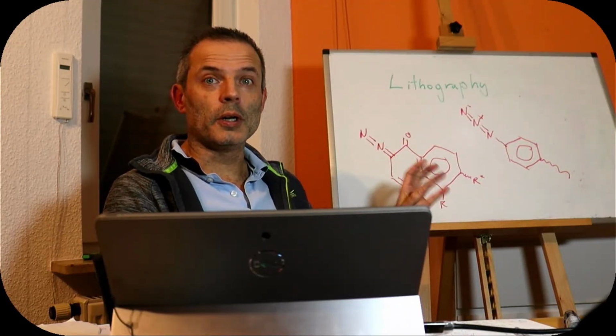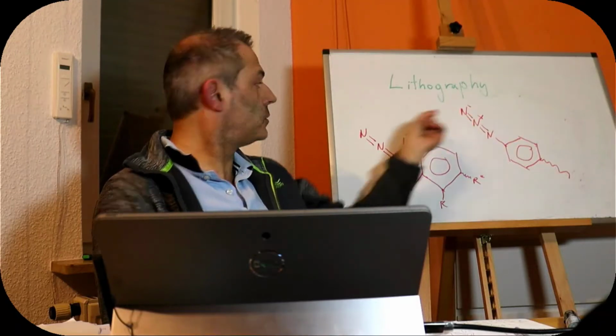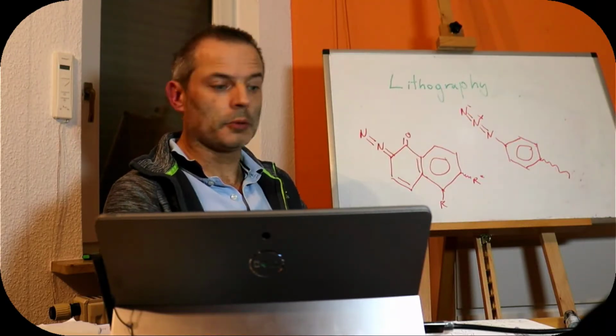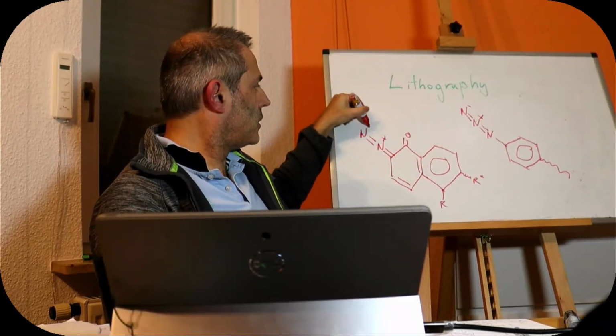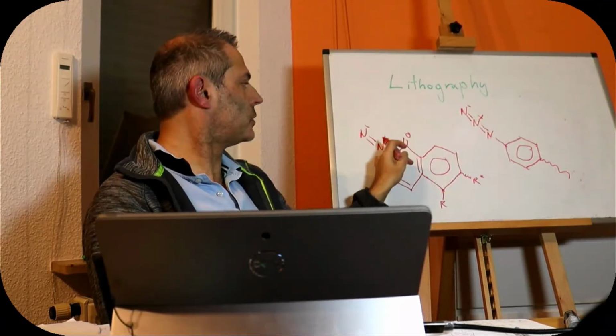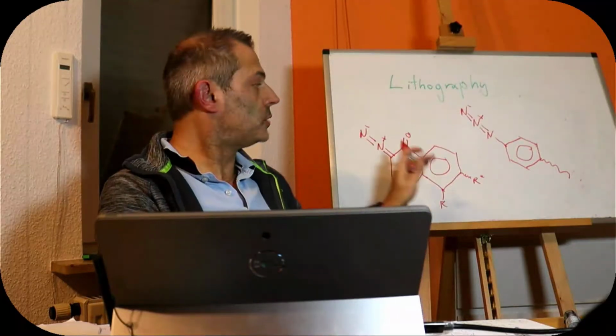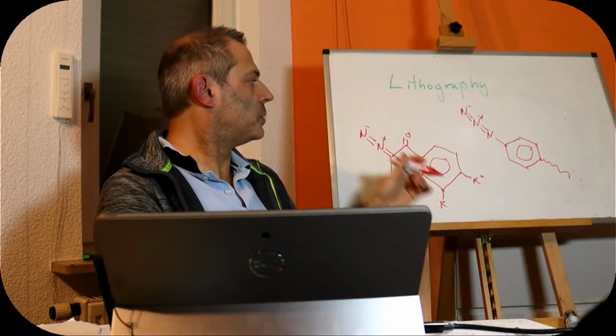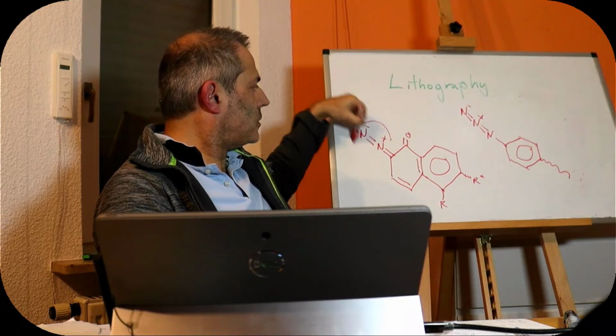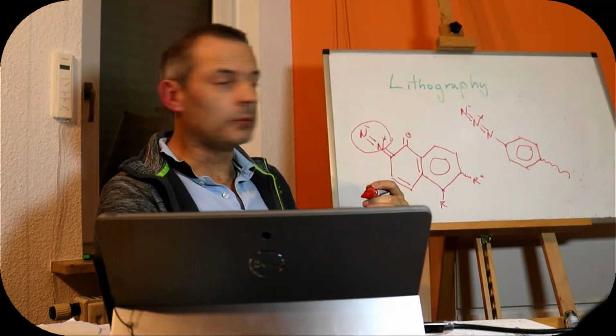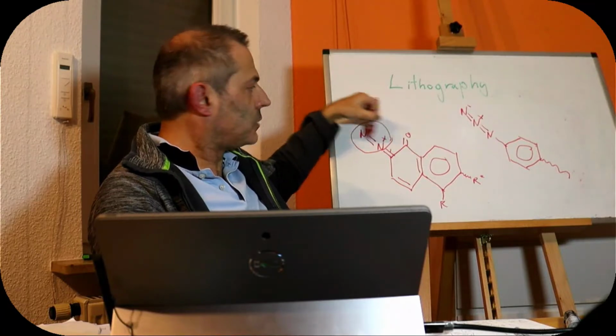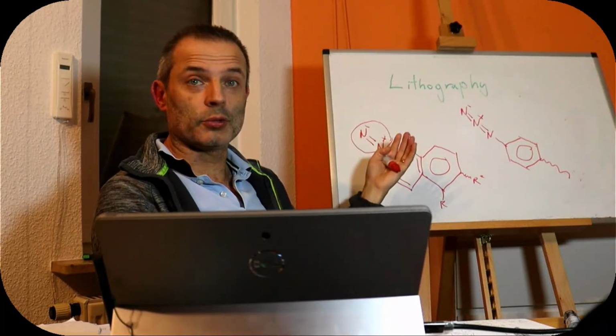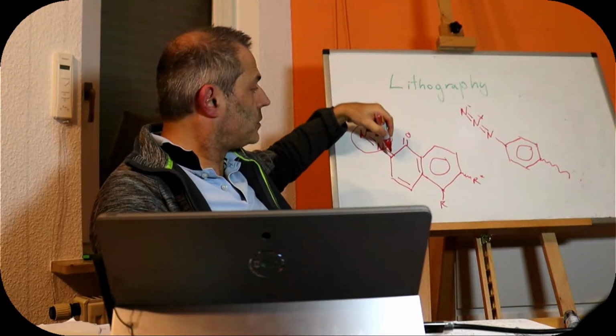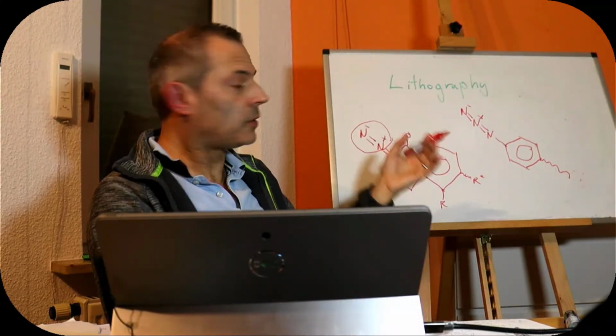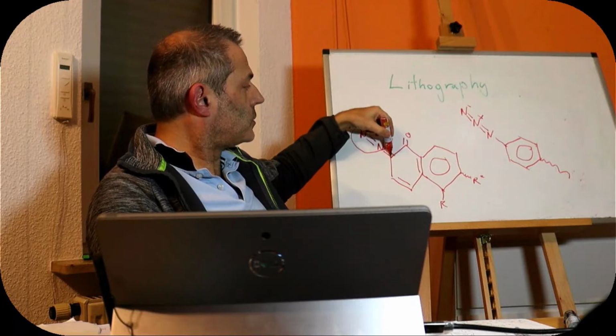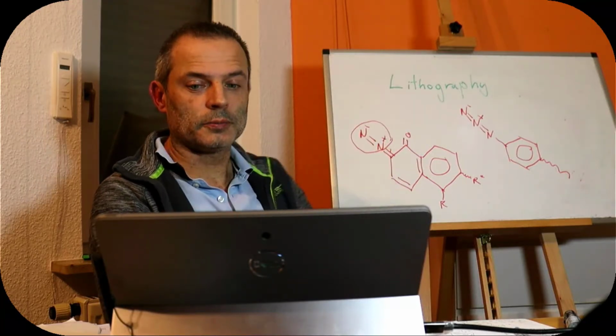The group that's going to absorb the light is the same one in these two, the nitrogen that has a partial charge imbalance, so a plus here and a minus here. This one's got 3 nitrogens and this one's only got 2. We'll start with this one because it's actually the slightly more common type. The nitrogen is going to try to leave when we excite it with light. So we're going to excite an electron out of the double bond into there to make a triple bond, and that will cause a rearrangement. It causes a rearrangement called a Wolff rearrangement, which moves this carbon up to behind this oxygen.